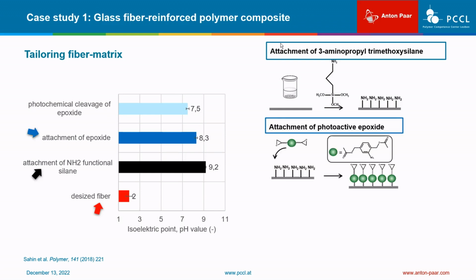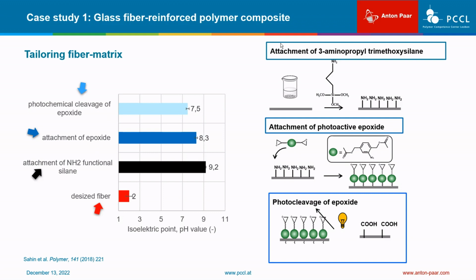The next modification step deals with the attachment of a photoactive epoxide. The isoelectric point of the modified surface shifts to pH 8.3. In the final process, a photocleavage of the epoxy groups triggered by light exposure shifts the isoelectric point to pH 7.5. After the modification step, the desized and modified fibers are embedded in a photocurable acrylate resin formulation. By performing single fiber pull-out tests, maximum pull-out force, friction strength, and apparent interfacial shear strengths are determined as a function of the coupled silane. The results reveal that the attached organosilanes lead to a significant increase in the adhesion strength.